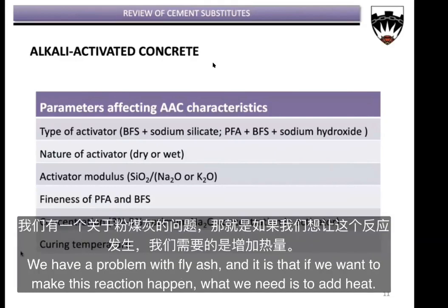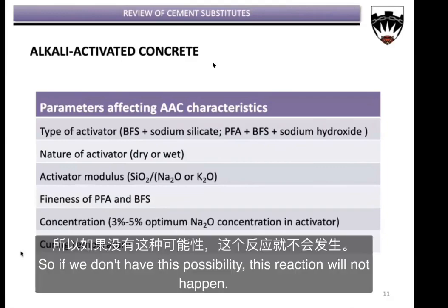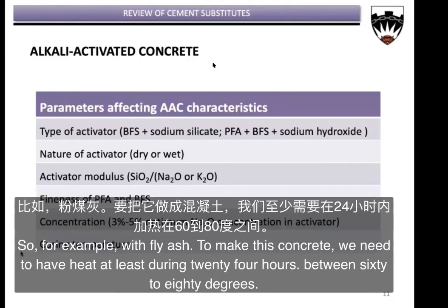We have a problem with fly ash, and it is that if we want to make this reaction happen, what we need is to add heat. So if we don't have this possibility, this reaction will not happen. So for example, with fly ash, to make this concrete, we need to add heat at least during 24 hours between 60 to 80 degrees, right?